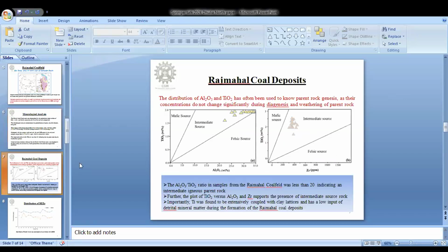So moving on to some of the graphs which we have supporting our observation regarding the origin of the coal deposits. The distribution of aluminum oxide and titanium oxide is often used to know the parent rock genesis, as the concentrations do not change significantly during diagenesis and weathering of the parent rock. What we found in our case was that since the ratio, which I already mentioned, was less than 20, it indicated an intermediate igneous parent rock being the origin.